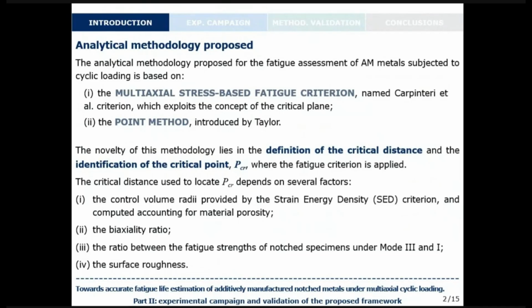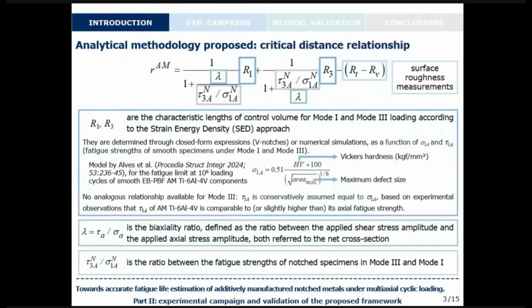So this critical distance is a function of four factors, mainly: the control volume radii provided by the SED criterion, and that are computed accounting for material porosity, the biaxiality ratio, the ratio between the fatigue strength of notched specimens under Mode 3 and Mode 1 loading, and the surface roughness. And here you can see the expression for computing the critical distance R_AM.